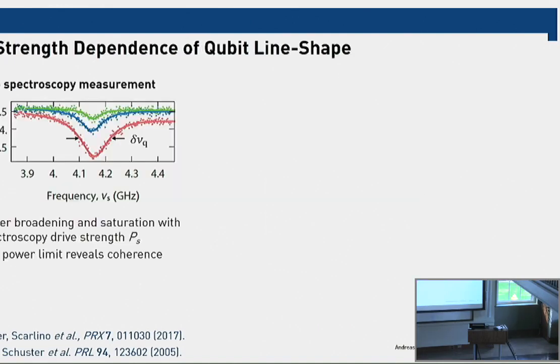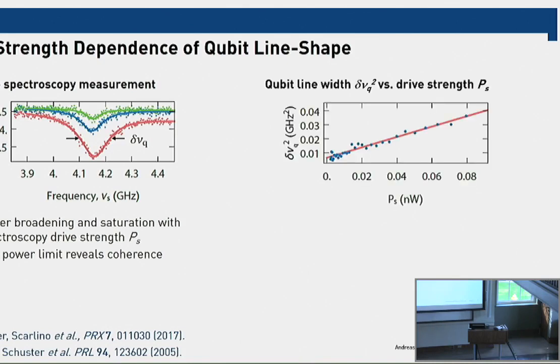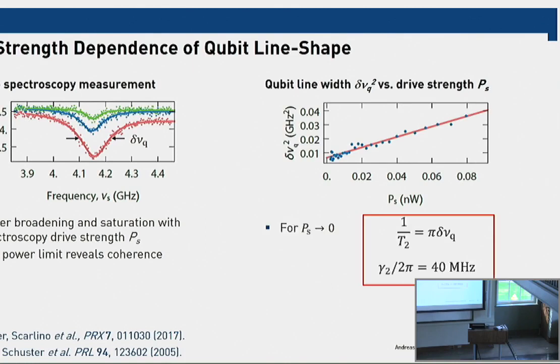So here's a spectroscopy of this double dot charge qubit for different microwave frequency drive strengths that are resonant with the quantum dot. And when the drive strength is large, you power broaden the transition, and if you turn the drive strength down, you will see the intrinsic line width of the double dot. And now you can plot the square of that line width versus the driving strength, and then you can get an estimate, maybe not a super accurate one, for what the line width of the quantum dot transition is at low drive strength, which in this case was about 40 megahertz or so, which was about a factor of 10 or so smaller than all these early experiments. So in this device we got both larger coupling strength and also better coherence properties.